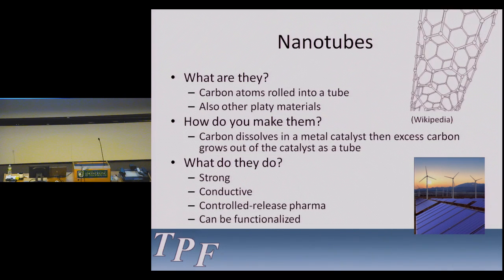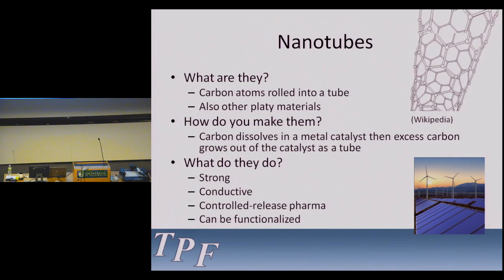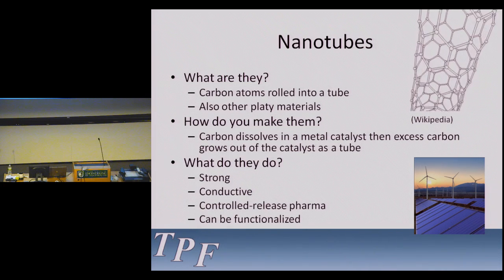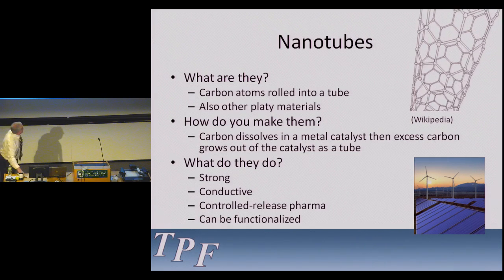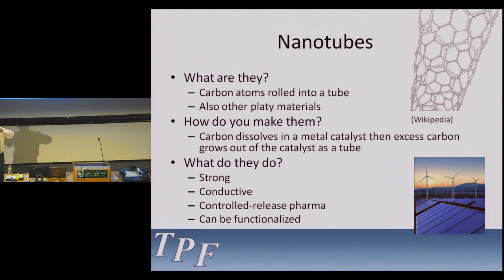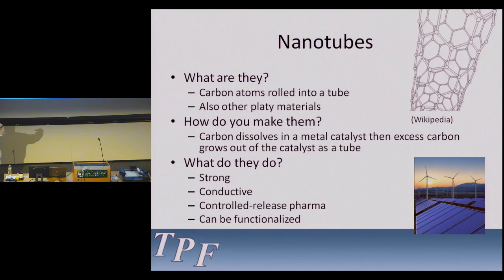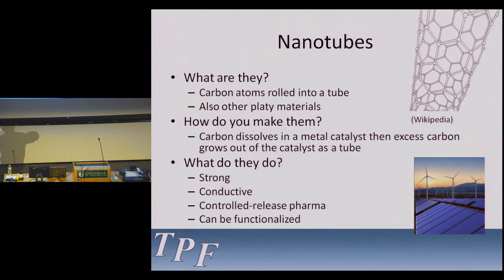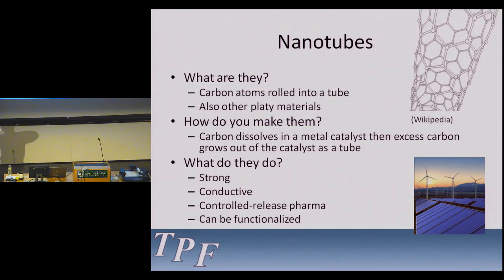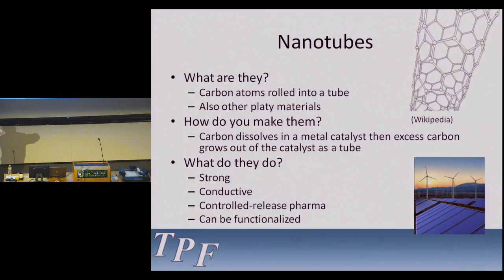Siemens, for instance, is putting them in the carbon fiber box structures of their wind turbines. And the reason for that is inside the blades is a box structure, which is really the structural strength. And in that you have epoxy, you have carbon fibers, and the weakest part is the epoxy that's holding the carbon fibers together. So you put much smaller fibers in there between the main fibers, which increases the strength quite significantly.